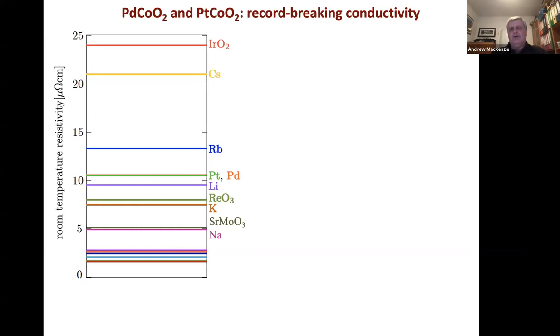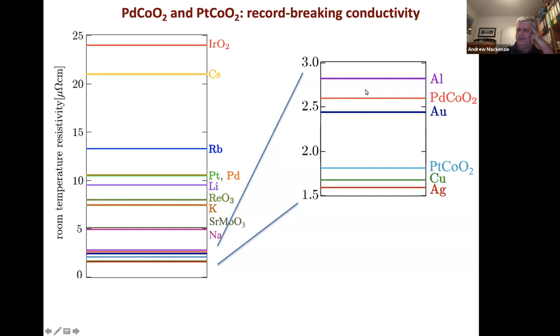What they did know, particularly at room temperature back in the 1970s, was that these things are extremely highly conducting. So here I'm showing you a graph of the room temperature conductivities of various famous elemental metals and a few of the most famously super highly conducting oxides. And you'll see there's a group at the bottom here which are too closely spaced to label on this graph. If I blow that up, you'll see it includes the Ashcroft and Mermin favorites like aluminium, gold, copper, and silver. And nobody who's done serious work on oxides would ever have expected metals containing the element oxygen, shall we say, to be in this group of super highly conducting metals at room temperature. But it's actually even more marked than that, because platinum cobaltate has almost the same room temperature resistivity as copper or silver.